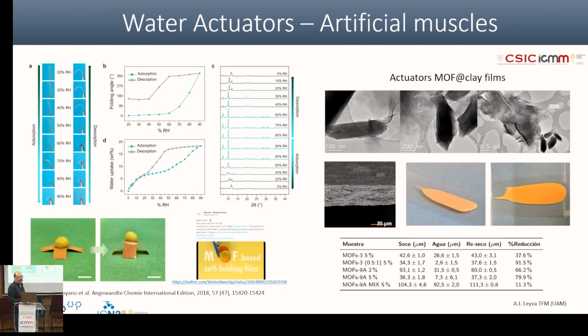So he started controlling the relative humidity when he understood that it has some sort of asymmetries inside, and then depending on the relative humidity that he exposed it to, he had a difference in the rolling phenomena, reversible, coming up and down. So we decided to collect water isotherms to correlate with the phenomena, and also with the crystalline structure at different relative humidity. So here we have an actuator. Okay, it's changing mechanically by an input and output of the host.